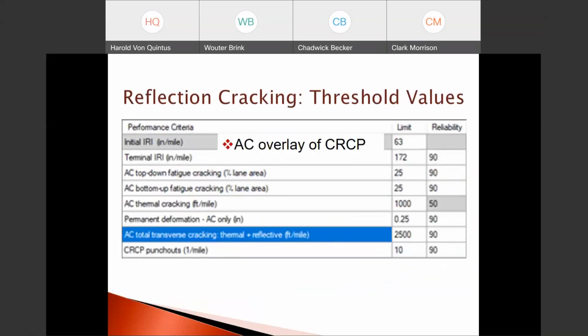Next is the AC overlay of the CRCP pavement. Again, it's recommended that the AC total transverse cracking, thermal and reflective, shown in blue, should be the same as the AC thermal cracking shown in the line item above. It's not shown to be the same here; that was just forgot to change. Generally, they should be the same threshold values. And then also the CRCP punch out shown in the lower row of the drop-down screen.